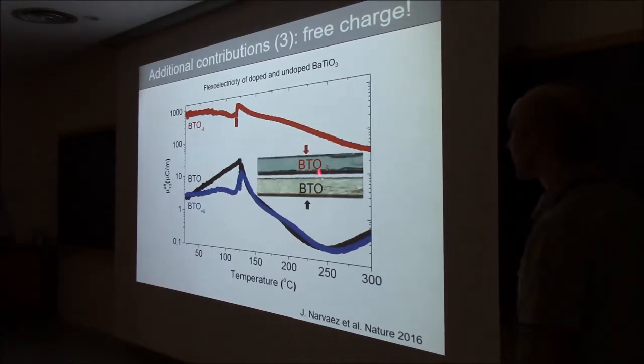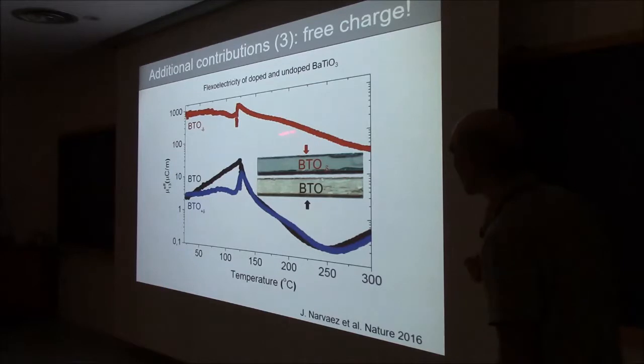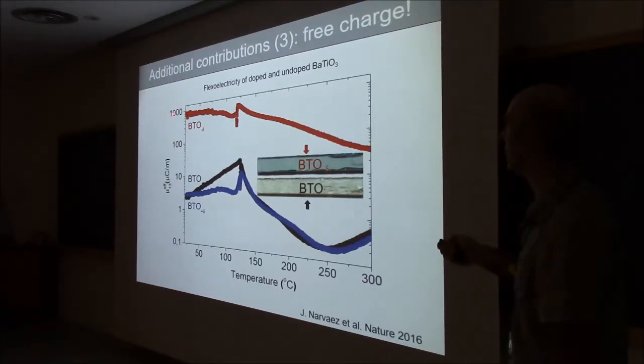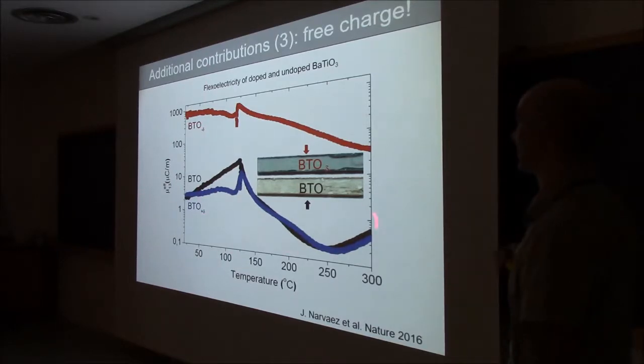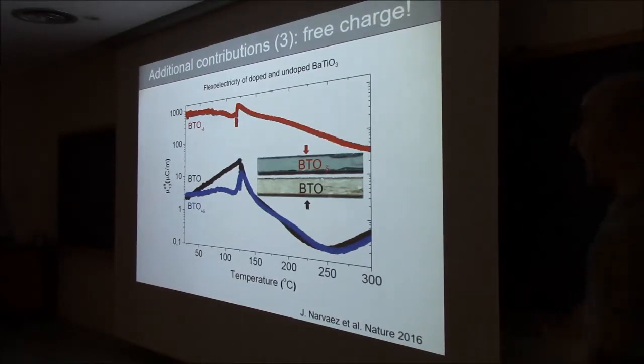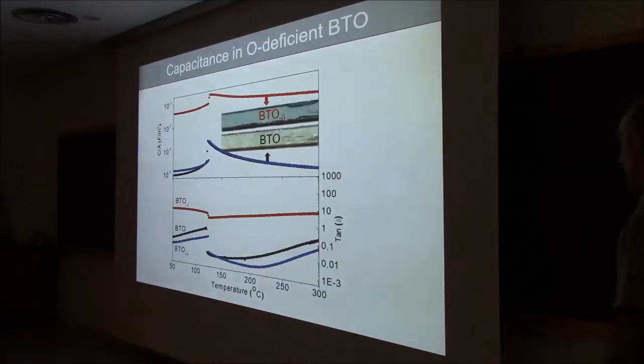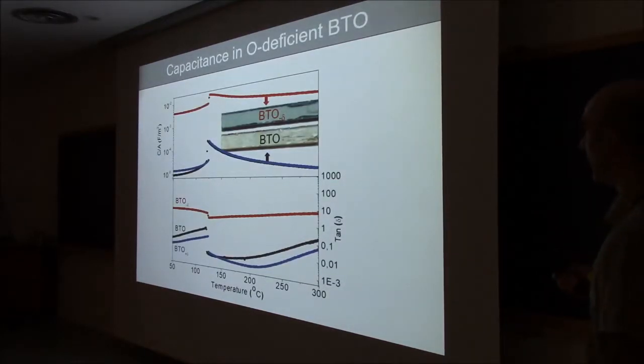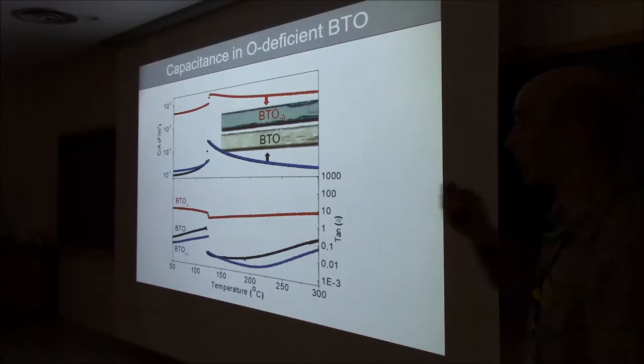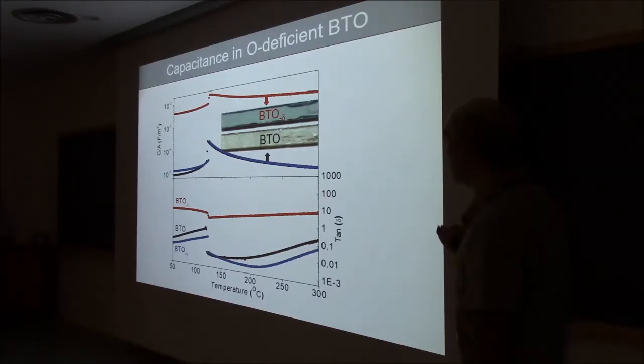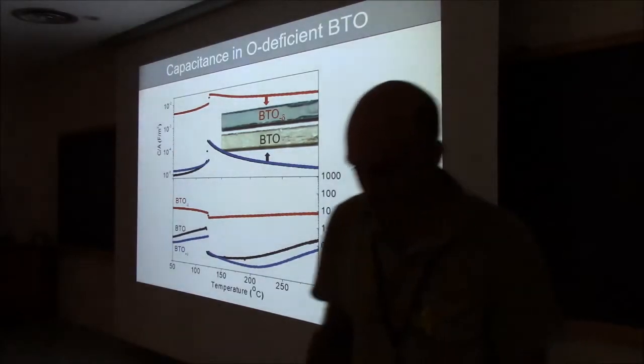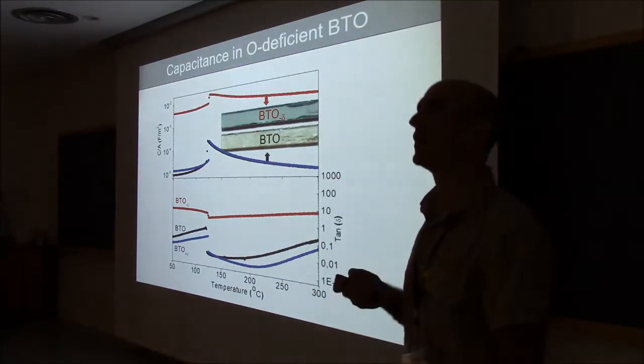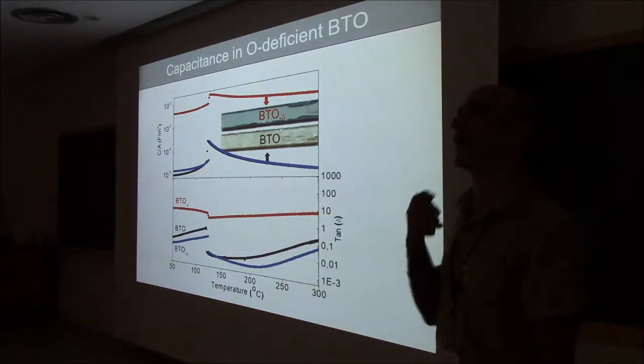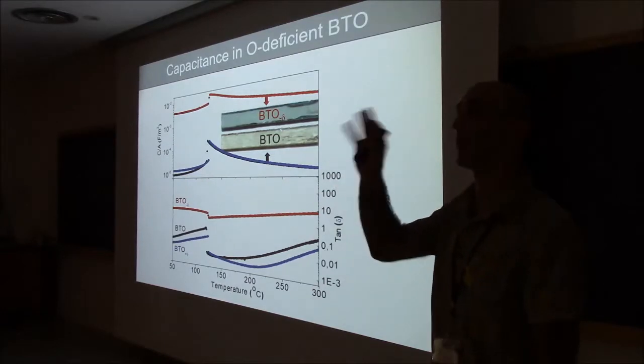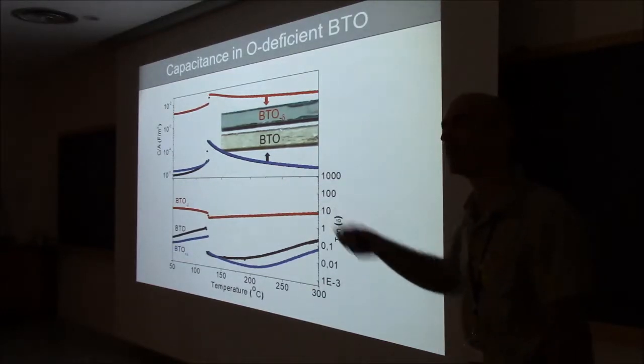Okay, so now it's more conducting, and if you now measure the flexoelectricity of this conducting, oxygen deficient BTO, you see a huge effect. Okay, thousands of times bigger than what you see in the insulating case. And we need to understand this. If you remember my talk from 2 days ago, if you have something that is not a perfect insulator, it might give you a giant capacitance. Remember the Maxwell-Wagner effect, barrier layer capacitor thing?